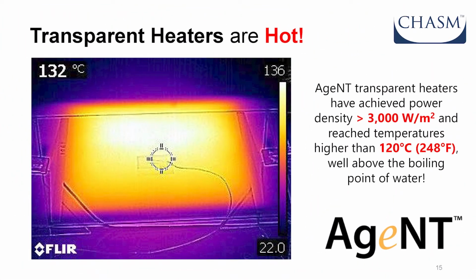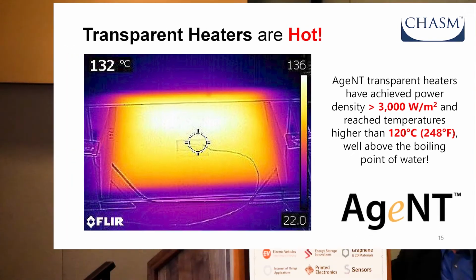Transparent heaters are really hot. In fact, that's proven at our booth, booth 107. This has been the hottest item at our booth. We are displaying a transparent heater. We have demonstrated transparent heaters that can achieve power densities in excess of 3,000 watts per square meter. This can generate temperatures that are well above the boiling point of water. Now, we really just need to be able to melt ice on a windshield or a lens, but we could boil water on these transparent heaters.